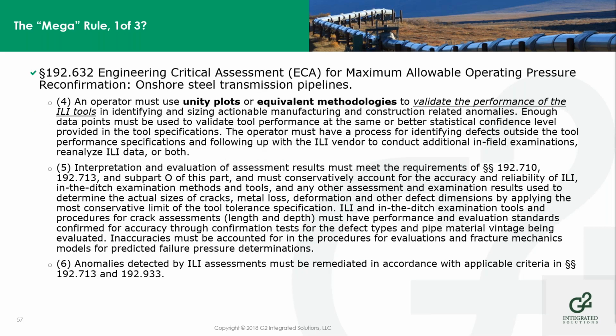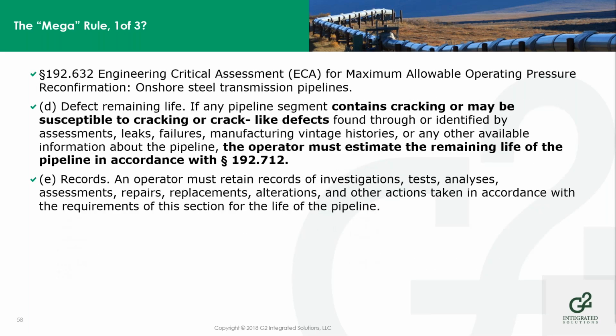An operator must use unity plots or equivalent methodologies to validate the performance of the ILI tools. So you run the ILI to follow this ECA process. You need to make certain that the data that you get out of that tool is valid and it's been confirmed, and you have supporting data that says it's good information and it supports your assessment. Inaccuracies have to be accounted for in the procedures for the evaluation of fracture mechanics models and predicted failure pressures. Calling our ILI contractors into task here to make sure we're getting good information.